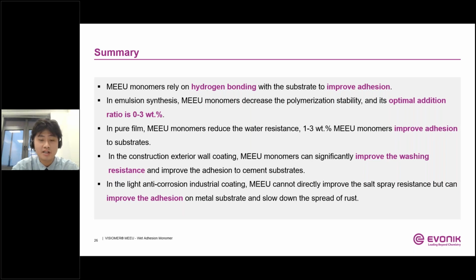In the construction exterior wall coating, MEEU monomers can significantly improve the scrub resistance and improve the adhesion to cement substrates. And in the light anti-corrosion industrial coating, MEEU cannot directly improve the salt spray resistance, but can improve the adhesion on metal substrates and slow down the spread of rust.